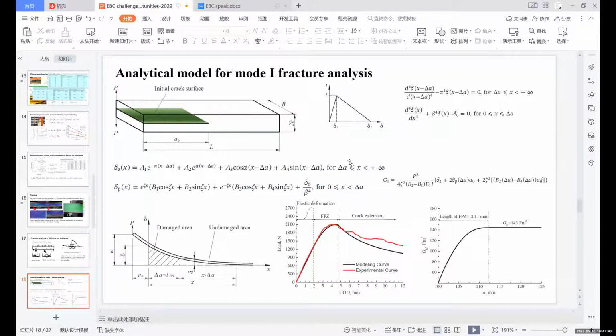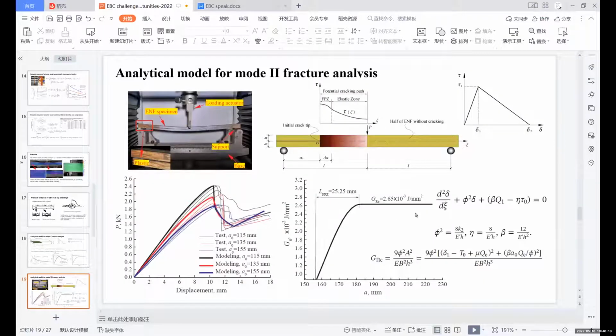So we developed a model to calculate the critical fracture energy of mode 2 and mode 1. This picture shows mode 1. So we use the trilinear cohesive model to predict the opening deformation, and we predict the load deformation curve and the energy resistance curve here. So this picture shows mode 2, the shearing in the plane. So we also have a good result compared to the experimental and the model prediction.